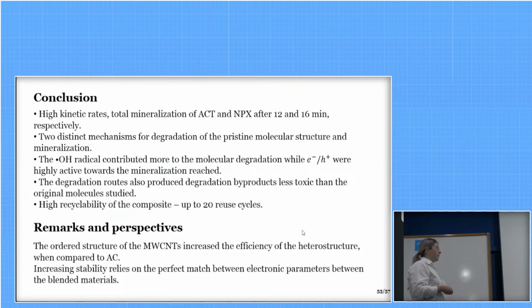Our conclusion from this study is that we were able to obtain really high kinetic rates with total mineralization of acetaminophen and naproxen after 12 and 16 minutes. Two distinct mechanisms for the degradation of the pristine molecular structure and mineralization occurred. We observed that the formation of the hydroxyl radical contributed more to the degradation, while the electron hole pairs were active towards the mineralization. The degradation routes also produced degradation byproducts less toxic than the original molecules studied, and we saw a high recyclability of the composite in up to 20 reuse cycles.